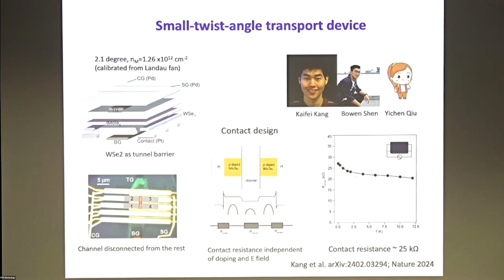So this is actually the contact structure that I want to talk a little bit about. This contact gate heavily hole dopes the twisted molybdenum telluride in the region immediately adjacent to the platinum electrode. The heavy hole doping is to reduce the contact resistance between the metal and the semiconductor exactly in this region. And the channel is gated by the top and the bottom gate. It turns out that we can write down roughly the contact resistance in this kind of series resistance circuit. And it turns out that the contact resistance is really dominated by this junction. This junction here, from heavy hole doping to variable doping in the channel, is quite transparent, as you will see. And so the contact resistance is totally independent of the electric field and the filling factor inside the sample, because this is only changed by the local gates there.